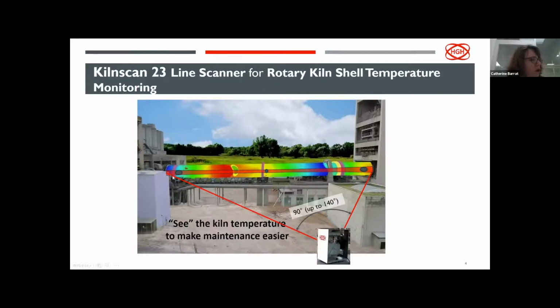The angle of sight of the scanner is at least 90 degrees, up to 140 degrees. Using this method, we are able to see the temperature of the kiln shell. This allows the operators to make the maintenance easier because it detects hot spots and measures brick and coating thicknesses.